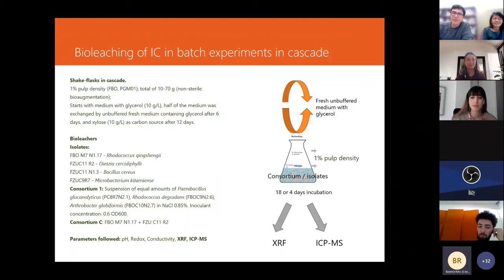So next we move to batch assays. We performed batch assays with a change of medium regularly for new medium, and we performed a cascade batch leaching assay. We tested our strains on bauxites, the strains that were selected with CarveMe, and we also tested a consortium that was built upon the results that were obtained with the plates, the YDC and YDM plates, and also the leaching of iron on goethite. Here you can see the consortium that was used and the isolates that were used on bauxite. So the consortium was used on residue FBO, and the isolates were used on bauxite residue.